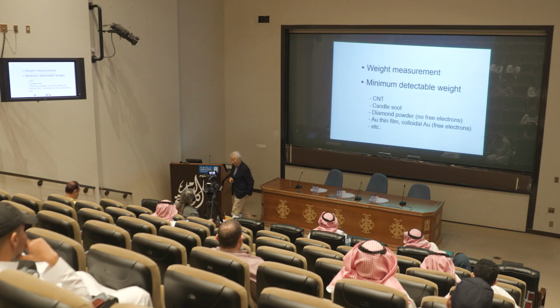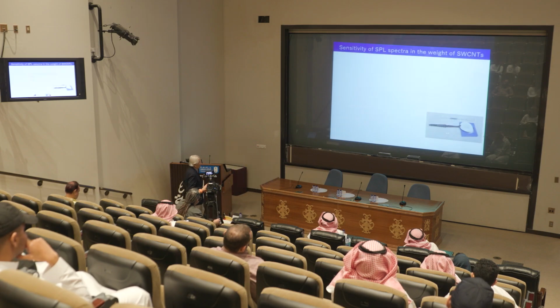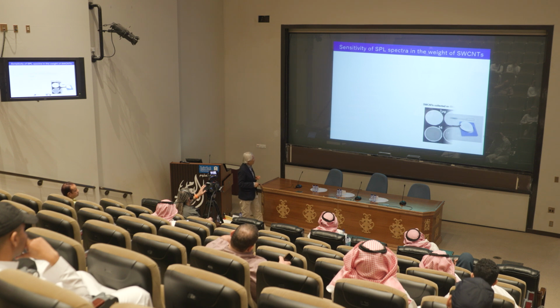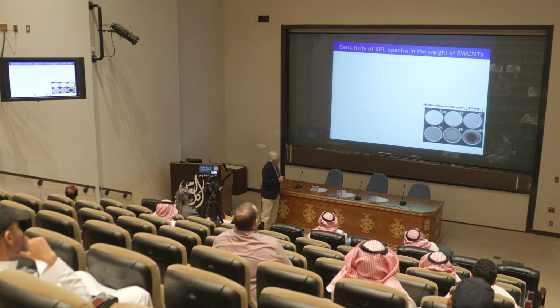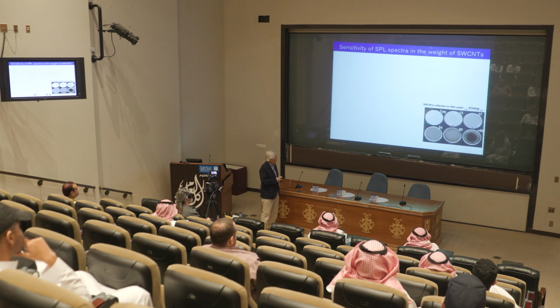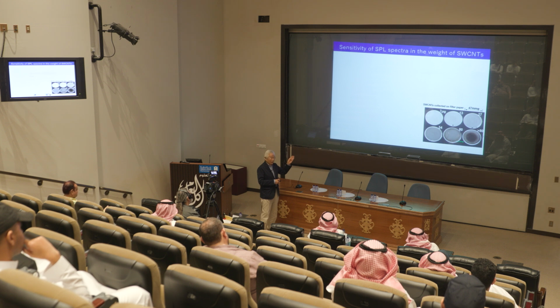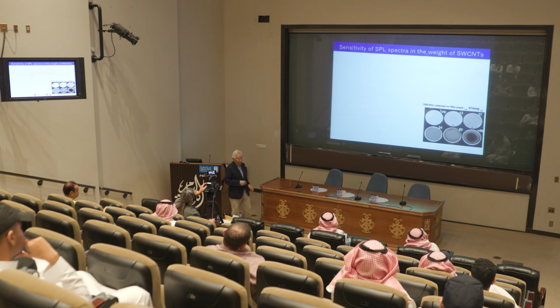So, I show you one of these. Okay. So this is my filtering paper, and I dropped the suspension of nanomaterial onto this paper. Very tiny amount, okay? This one, 7 microgram. It's almost white, and then I increased the amount of suspension, in this case the carbon nanotube suspension, okay? So this is 80 microgram. Then I listened to the sound from these